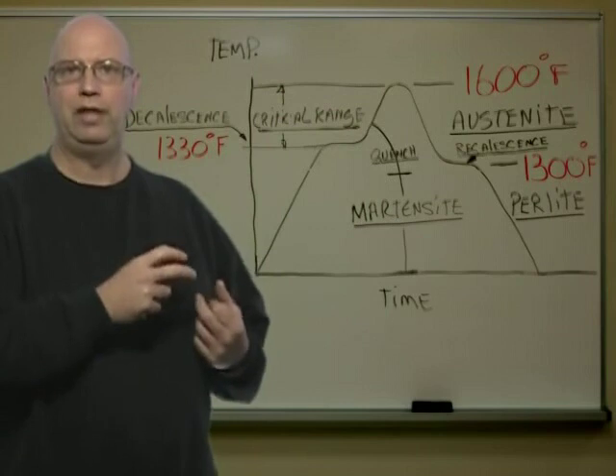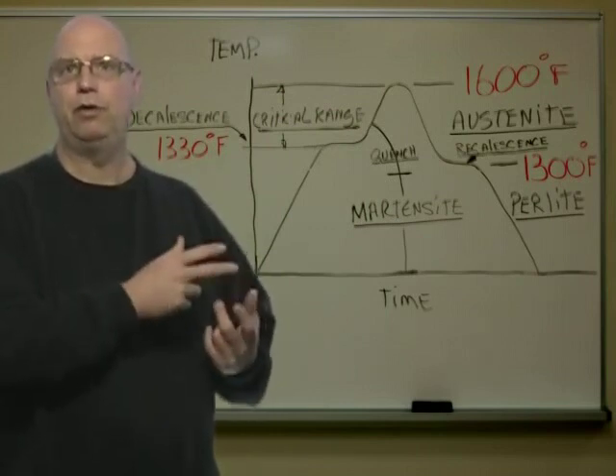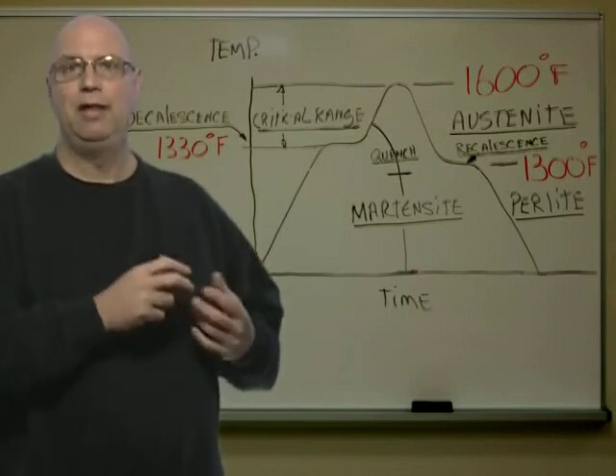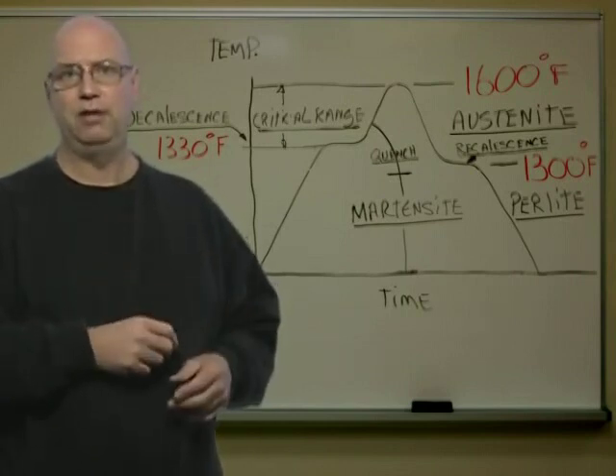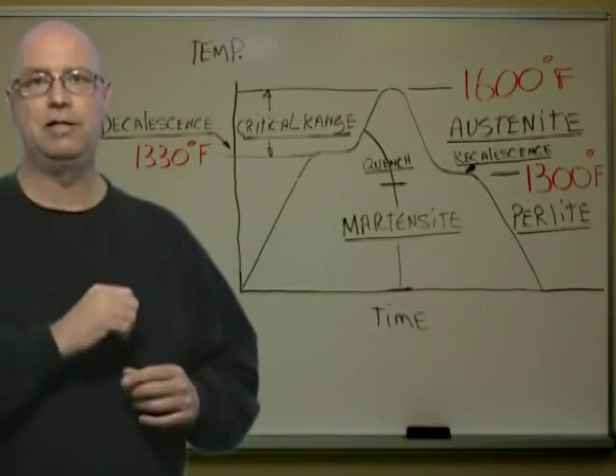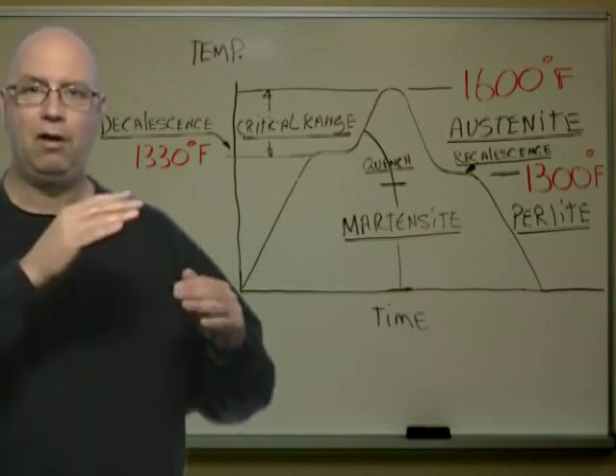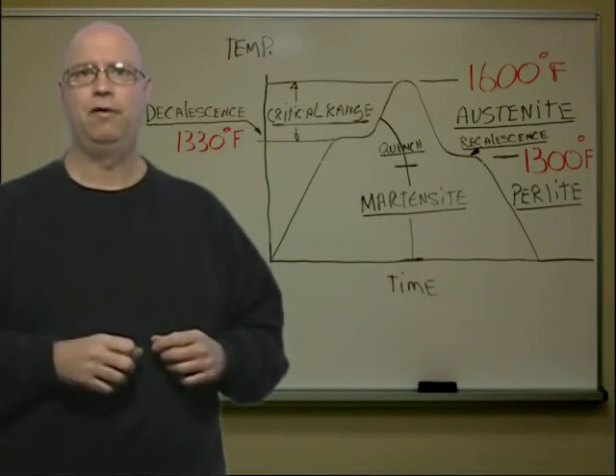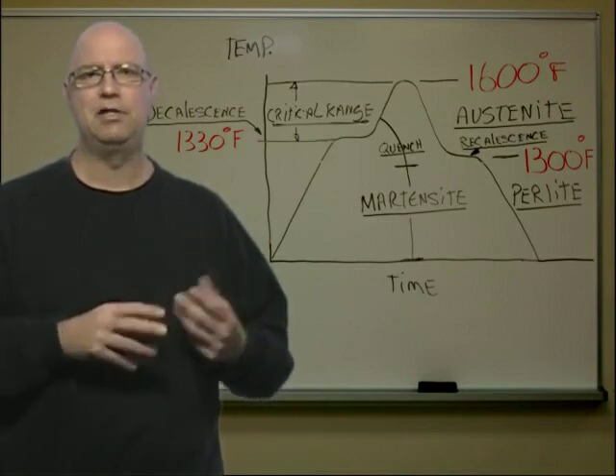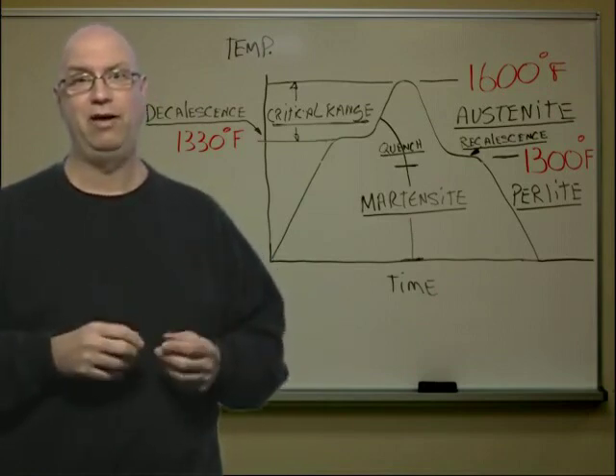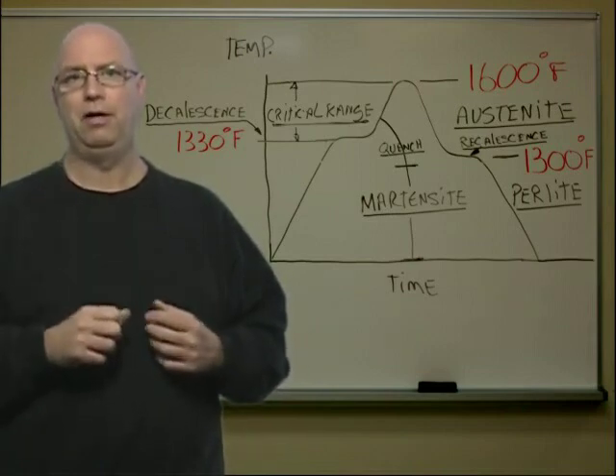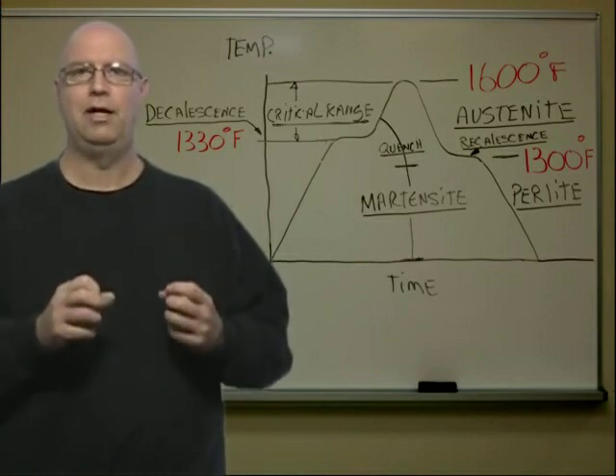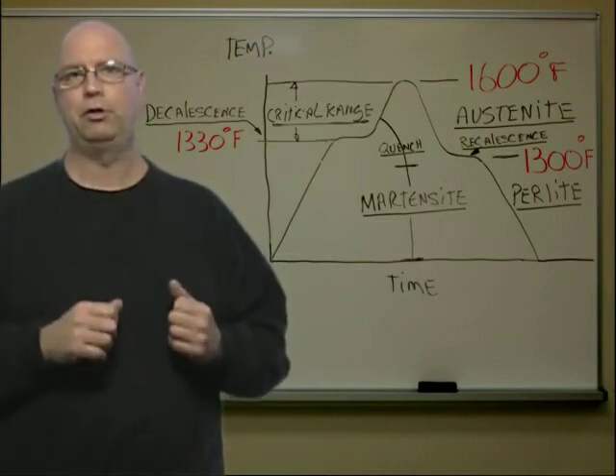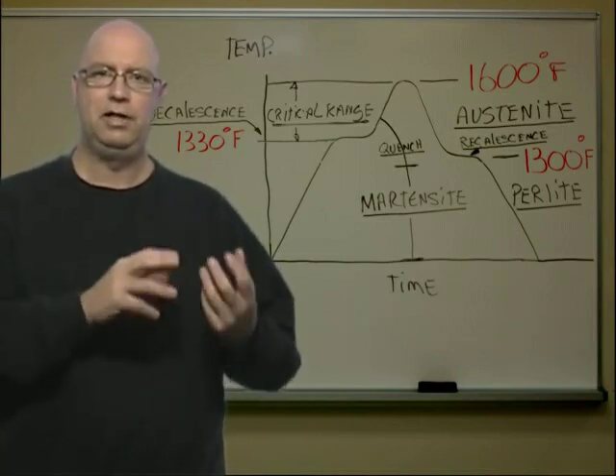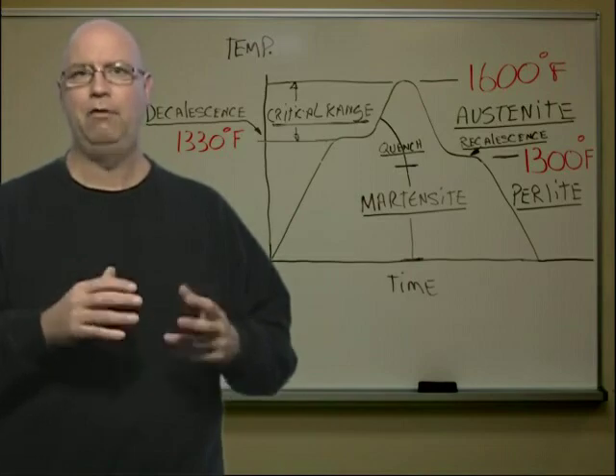If we look at it as a graph, we can see that as the steel warms up and it hits 1330 degrees, it stabilizes. That is the decalescence point for most steels. Now anything above the decalescence point right up to that 1600 degrees, well, all that area is in the critical range. Now, if we can say that most steel's critical range starts at the decalescence point around 1330 degrees Fahrenheit, well, we can't say as much for the upper limit of that critical range, because we have to realize that less carbon means higher temperatures in the critical range. So the less carbon a steel contains, the higher the upper limit of the critical range.